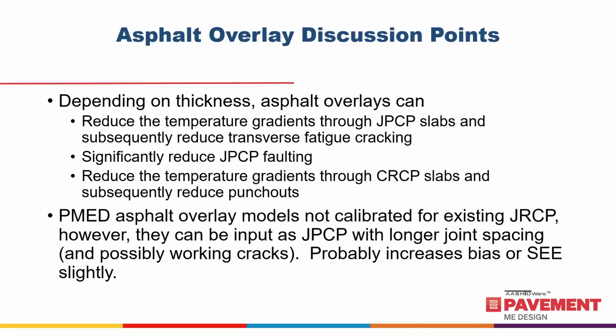Now, in this case here, as far as doing a reinforced concrete pavement, models weren't calibrated for them, but you can really just input them as a jointed plain pavement with longer joint spacing, and if you have working cracks. So let's say common jointed reinforced pavement length in decades past was roughly 60 feet or a little over 60 feet. So if you go out and do an assessment of a JRCP and you see consistent mid-panel cracks at roughly 30 feet, you could actually model this as a JPCP with 30-foot joint spacing. Is that completely correct? No, it's not. You may have a little bias or a standard error increase by using a jointed reinforced concrete pavement in place of jointed plane. I don't think it's going to be much though, so I think I would feel pretty comfortable doing this.